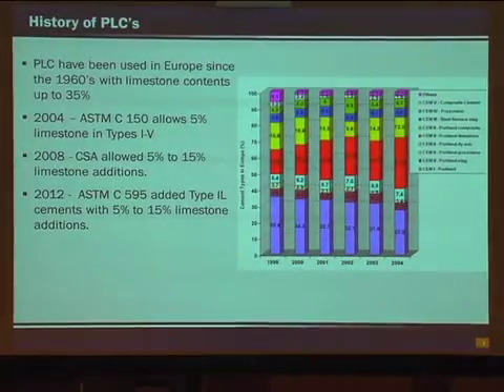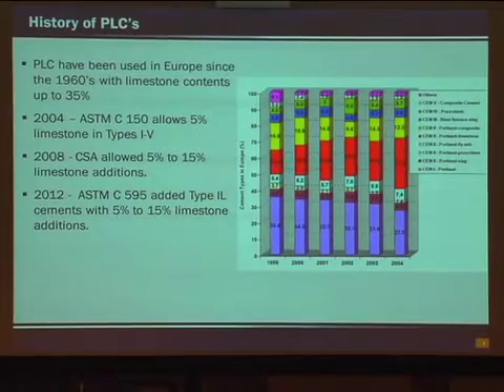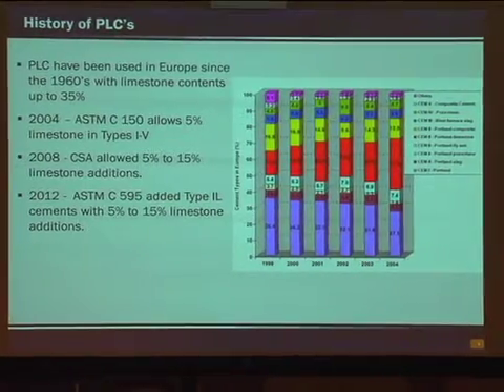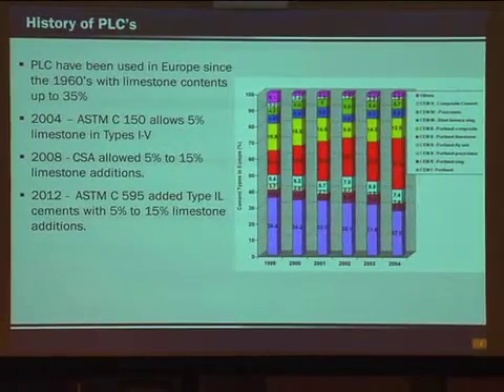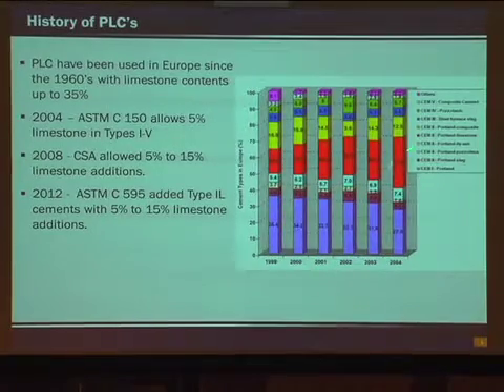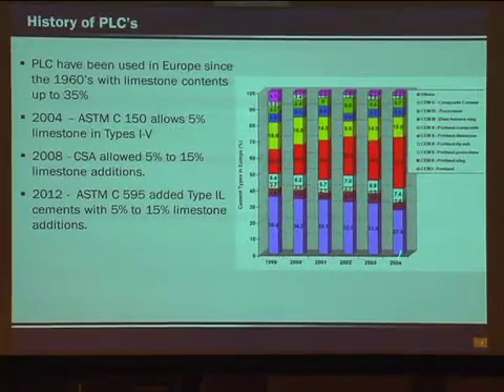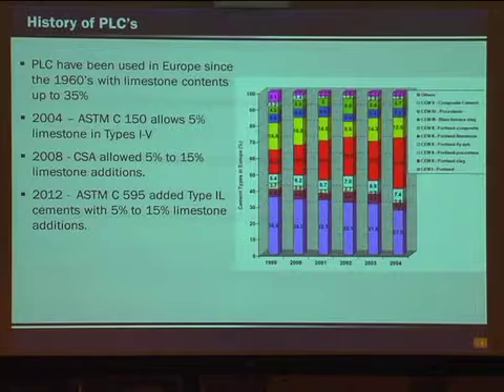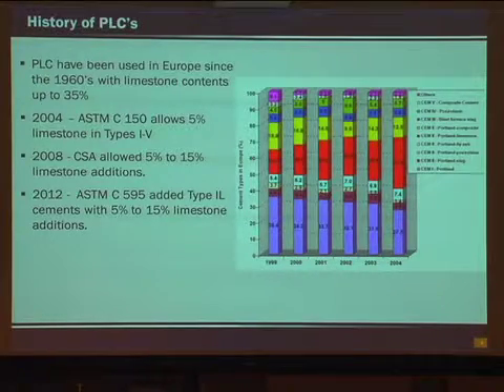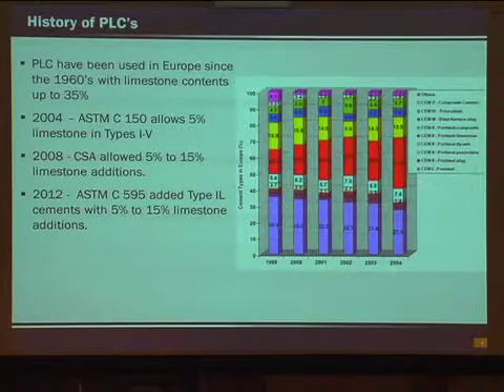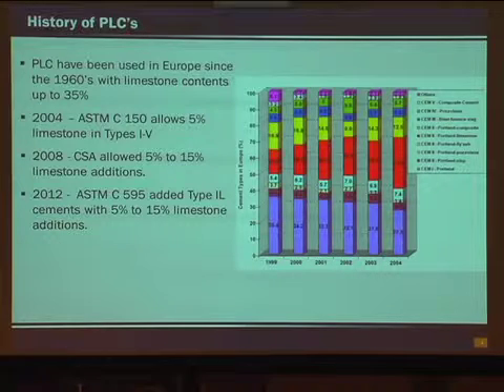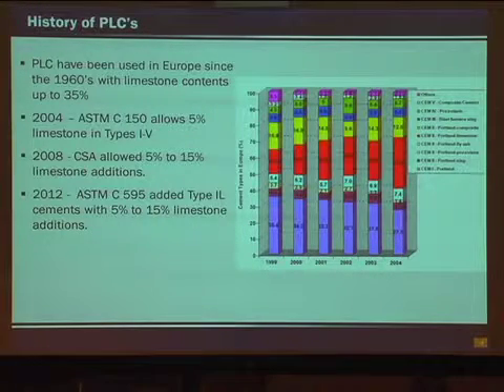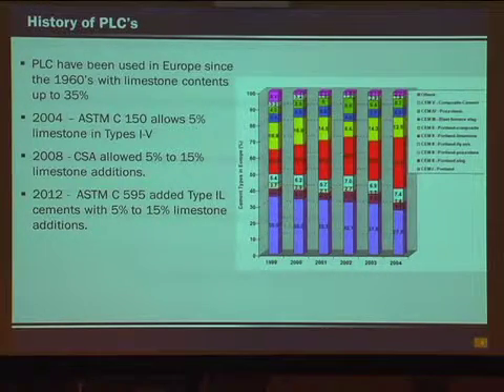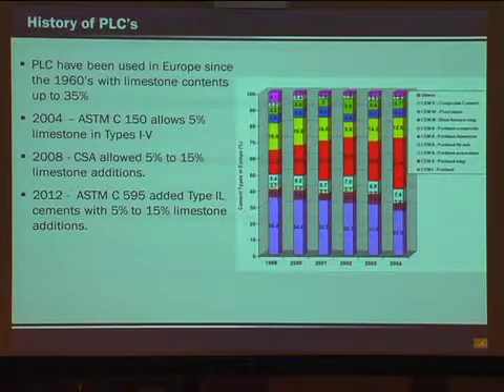Just a brief history. PLCs have been used in Europe since the late 60s. You can see by the plot, this was I think 2004 data, about a third of the cements used in Europe are PLCs. They allow up to about 35%, and the norm is typically around 20% limestone content in these cements. So they've had very good success with these cements in Europe.